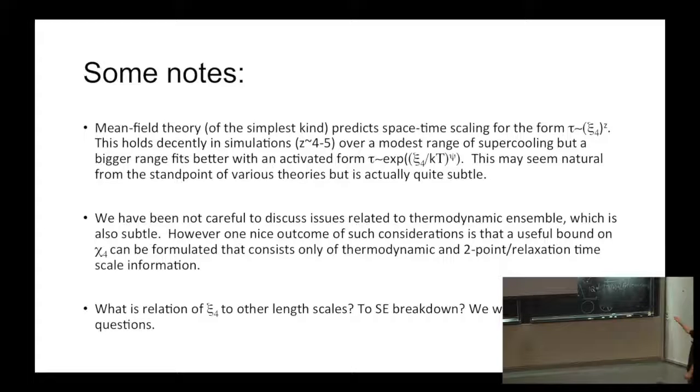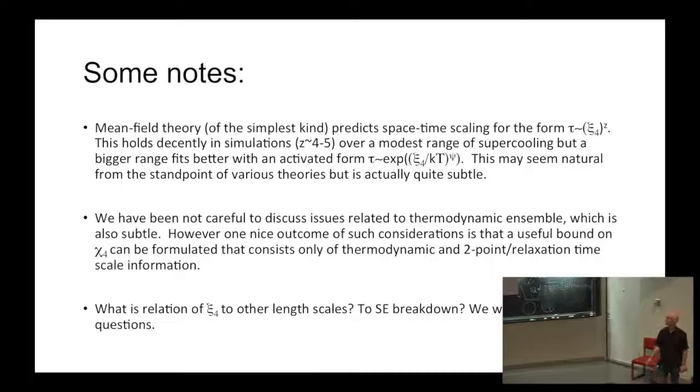And the power law that the mean field theory predicts, however, is very large. So the length scales grow very slowly. The actual power law that you can fit over some restricted range is something like 4, let's say. In the mean field theory, it's something like 9. So it's quantitatively wrong, but qualitatively right.